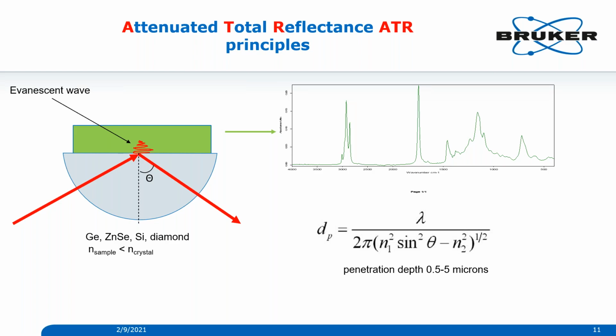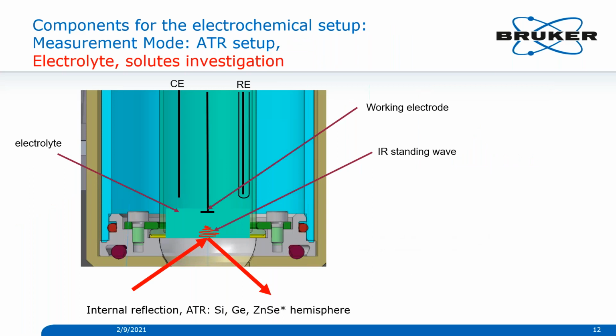How far light will penetrate inside the sample depends on many factors: the wavelength of light, the refractive index of the sample, the refractive index of the crystal, and also the incidence angle. So now let's take a look and use this design for electrochemical studies. You can see how it works. We use an internal hemisphere made of silicon, germanium, or zinc selenide. We shine infrared light, and it will create an evanescent wave. In this configuration, the working electrode is above the surface of the crystal, and the evanescent wave only penetrates into the electrolyte. So for this setup, we measure only what's going on during electrochemical reactions inside the electrolyte. We are not talking about surface chemistry on the working electrode.